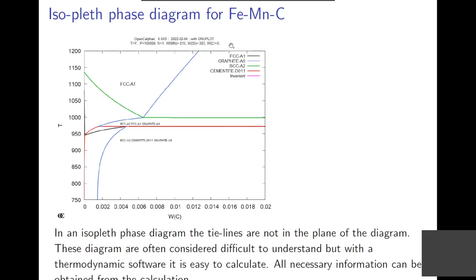So I took a diagram, iron, manganese, carbon. This is a stable phase diagram. Actually, I should have suppressed the graphite when I did this, because graphite you will never find in a steel. Graphite has a molar volume which is much larger than the other phases here, so you create a lot of stress in order to obtain graphite. But this is actually the stable diagram.